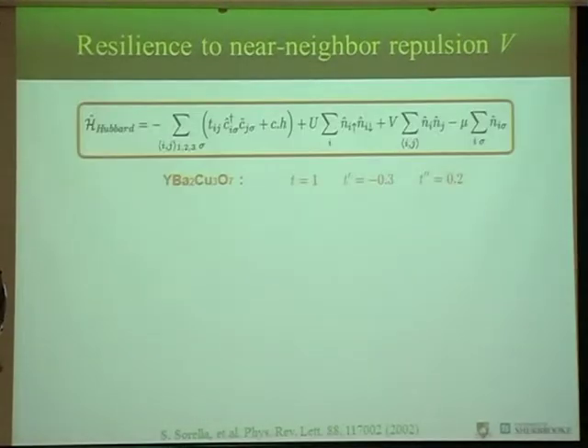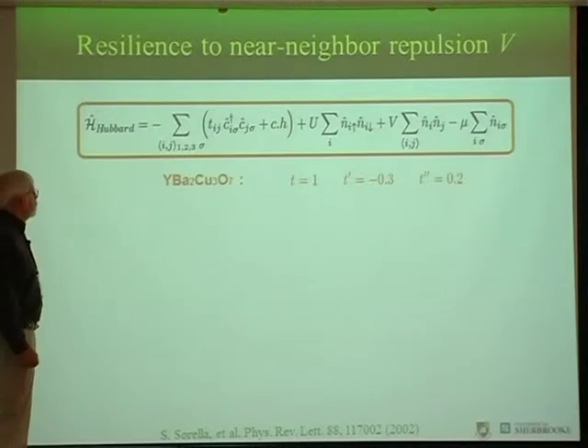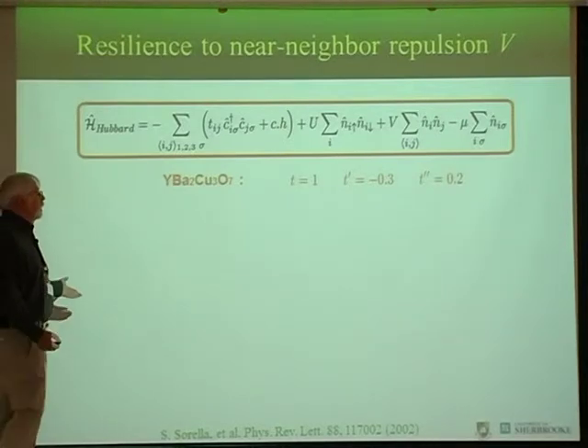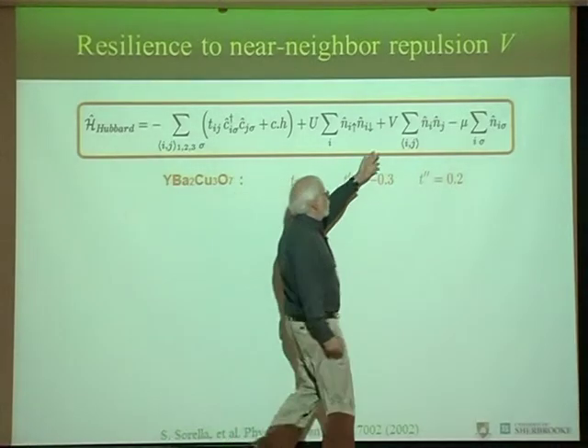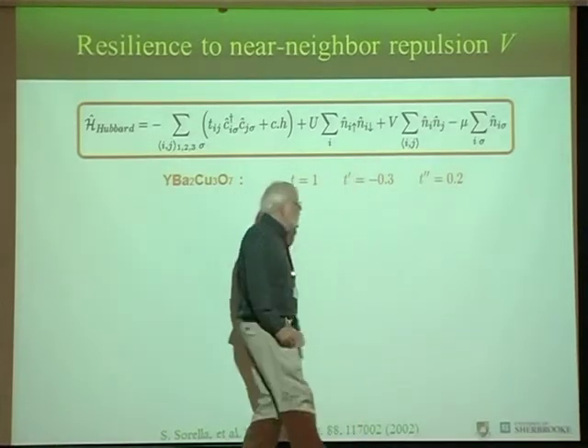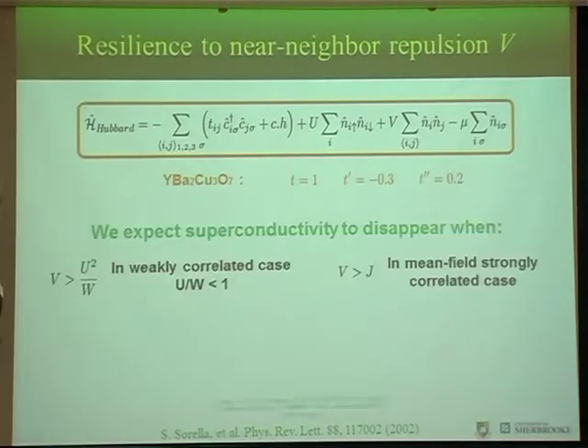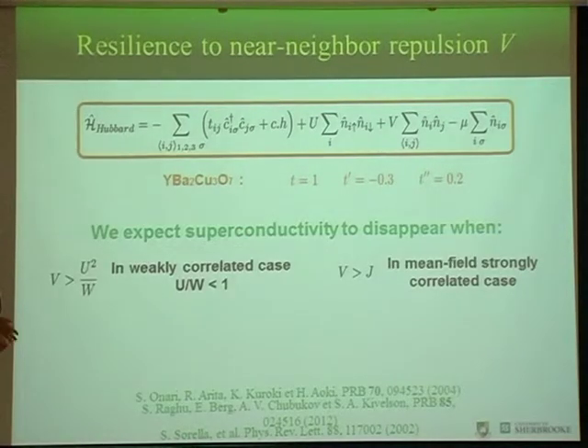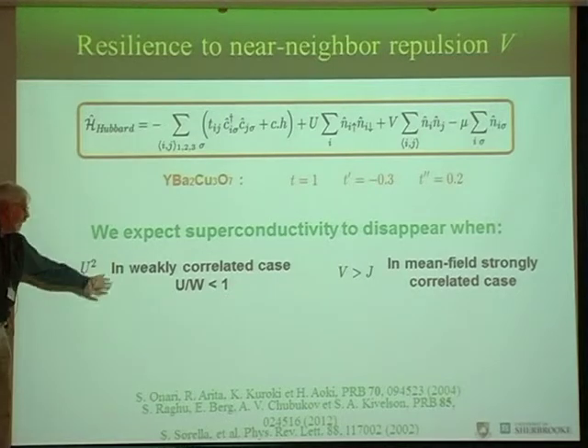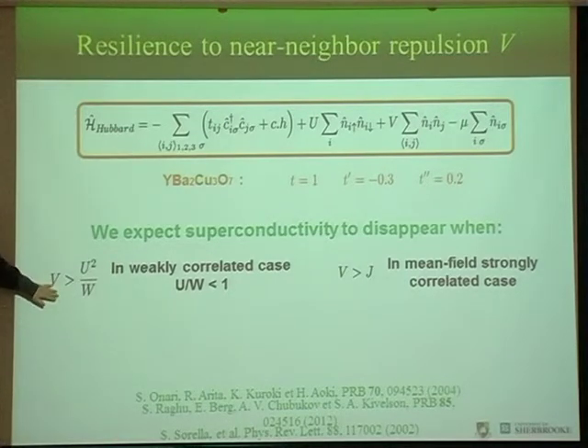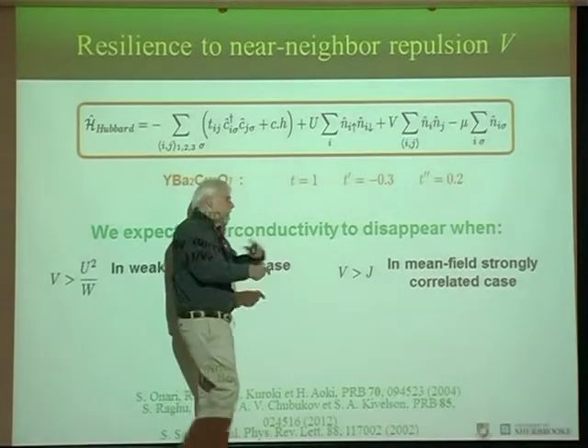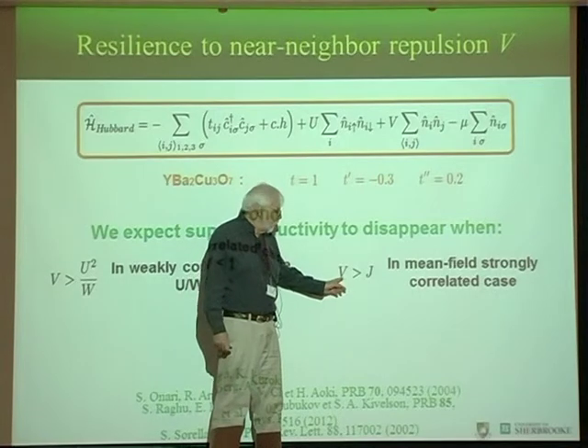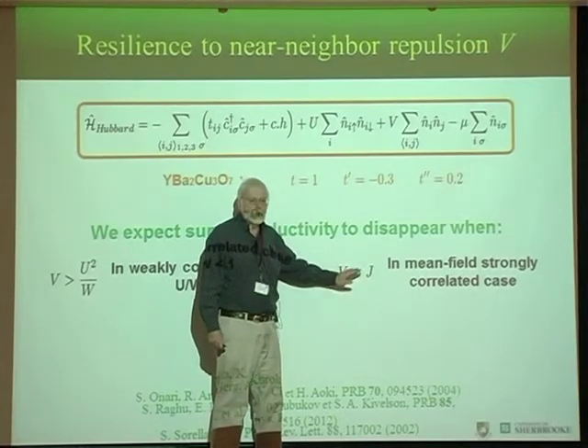Okay. Now, nearest neighbor repulsion. Well, the Hubbard model is nice, but we know that in real life there will be repulsion. And this is very worrisome because, in fact, it looks like a killer. If you look at the weakly correlated case, there are several papers that show that if V is larger than U squared over the bandwidth, you destroy superconductivity. If you look at the mean field way that I showed about superconductivity, this Varma-Schmidt ring, if V is larger than J, no more superconductivity.